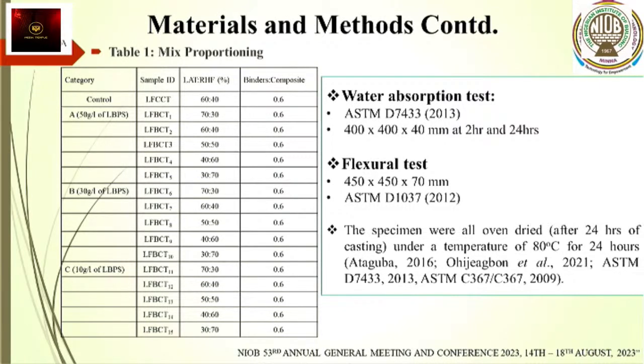size produced was 400 by 400 by 40 mm, and it was kept in the oven for 2 hours after molding before it was now cured. Then for flexural test too, we use a 450 by 450 by 70 millimeter sample, and the code used there was ASTM D1037 of 2012. The specimen were oven dried after 24 hours of casting under a temperature of 80 degrees for 24 hours according